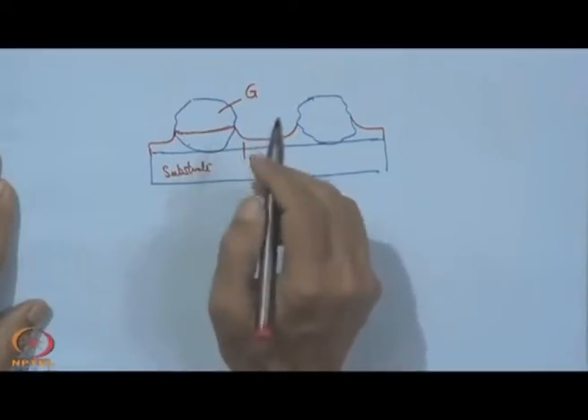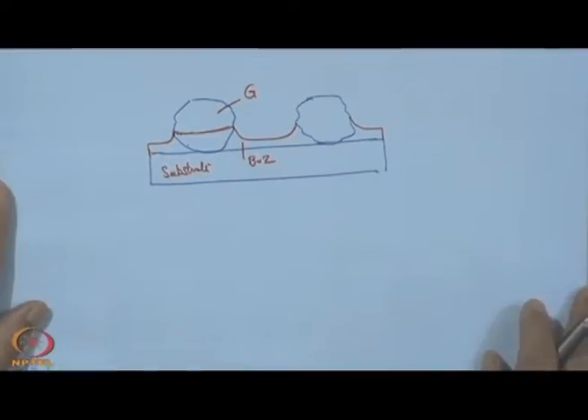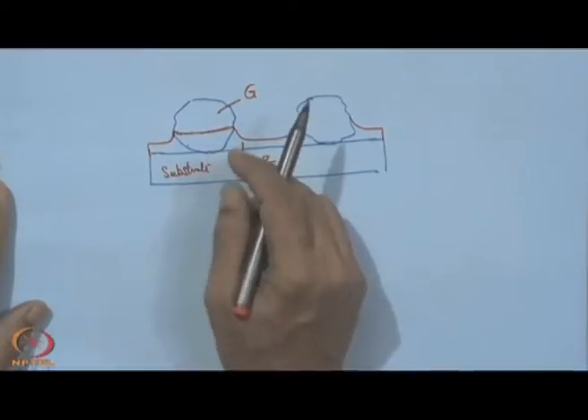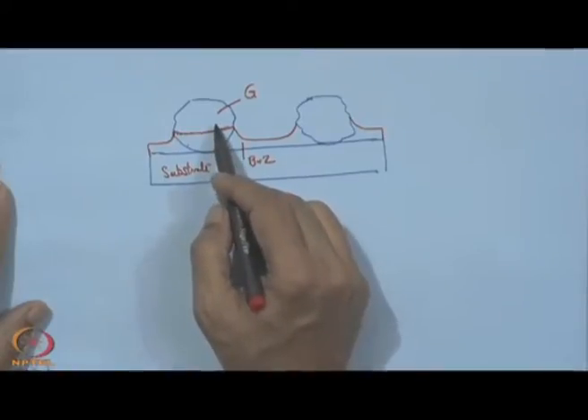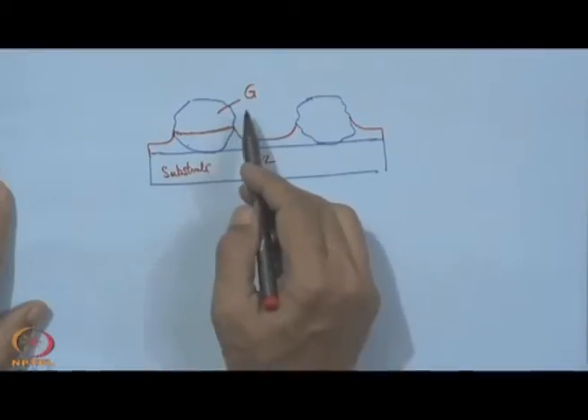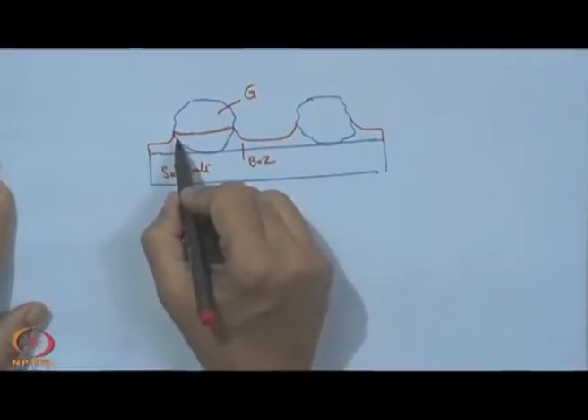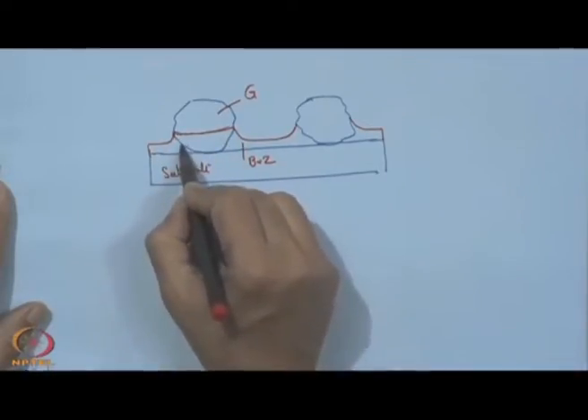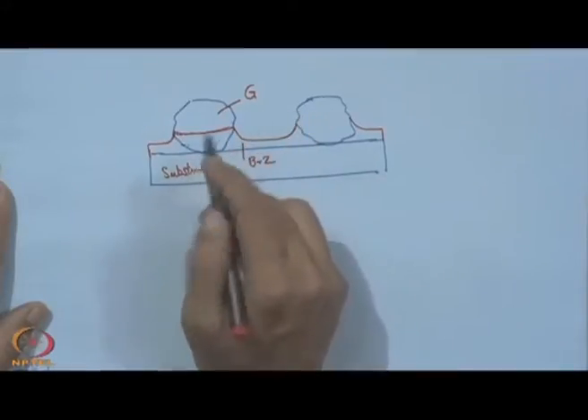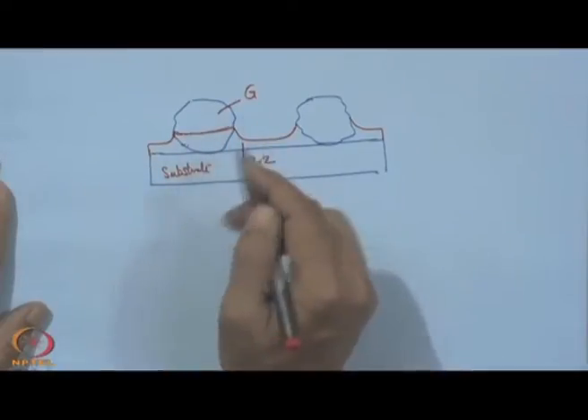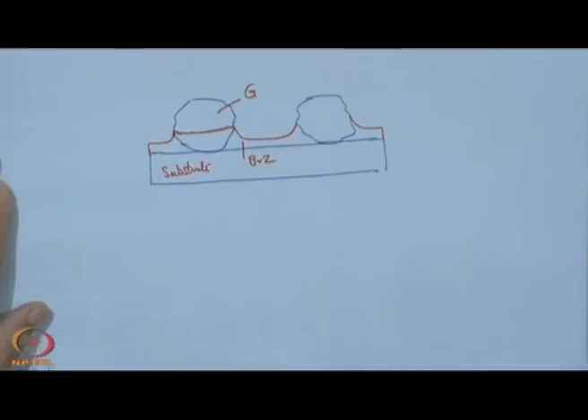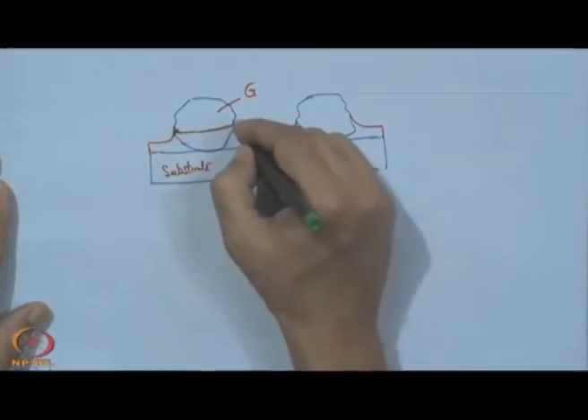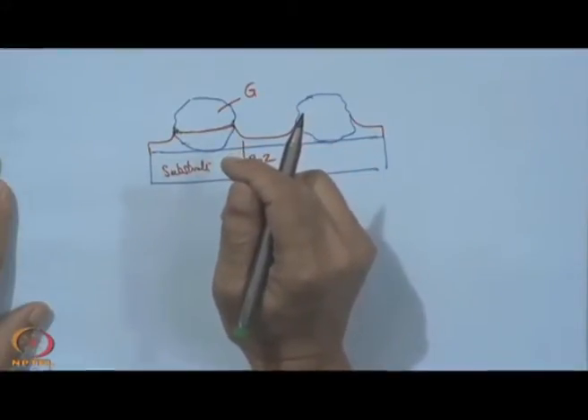Now, during cooling, the braze alloy, because of its high thermal conductivity and thermal coefficient of expansion, will cool at a faster rate, and the contraction will be larger in comparison to that of the grit material, which can be diamond or CBN. And exactly this material which is covered by the braze alloy will be under compression because of this contraction. However, the portion above that will be free, and as a result one may find some kind of crack here, and this will lead to a disastrous failure.